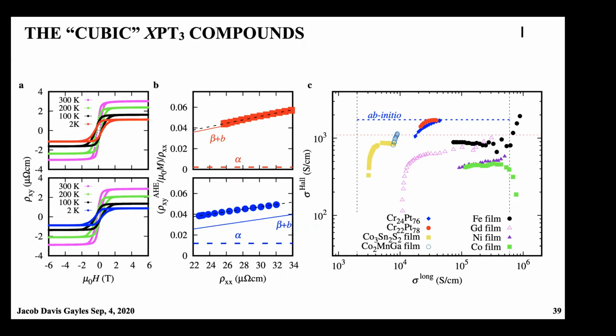And of course, if you have a ferromagnetic state, you easily have a spin up and a spin down state following in parallel, and so the effect could be small. But if you have an antiferromagnetic state, maybe you have an inversion, and maybe you have two of what you call the majority states and two of the minority states. And so it could be different. Yeah, I think the anomalous Hall effect would be 0 because you don't have these symmetries for the crystal Hall effect. But for spin Hall effects, it may also be interesting.